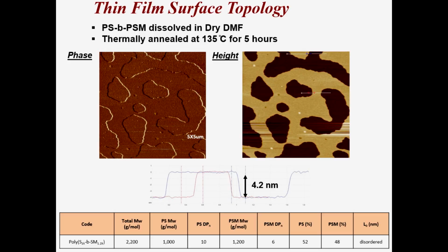If I take the polystyrene polyglycerol methacrylate precursor and I cast a film, and this film happens to be about 15 nanometers in thickness, I undergo this conversion to the hydrophobic-hydrophilic polyglycerol methacrylate. And with scanning probe microscopy, this happens to be a height image. This is a phase image. Phase image, nothing, you don't see much contrast, and the reason is that you have polystyrene on the surface. If I look at the height image, you see these very distinct changes in the height. And these height changes correspond to 4.2 nanometers.